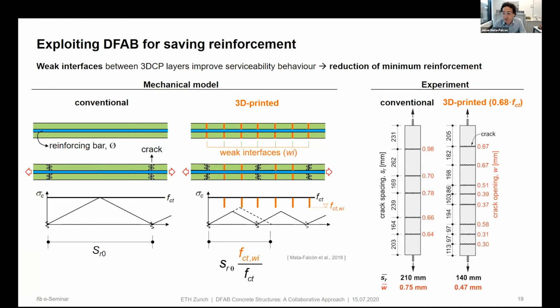There was a question in the Q&A regarding other presentations about these weak interfaces that other presenters have discussed. And I would like to introduce a more provocative point of view: is this always negative? Because I have to admit that regarding durability, it's something to be figured out, because porosity is higher close to these weak interfaces. So it's to be figured out if, with a conventional concrete with a crack width of 0.75 millimeters, is this better than having no cracks with the weak interface?